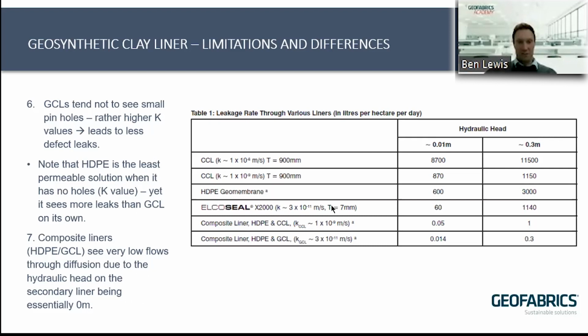And this chart here is showing the impact of a composite liner effect with HDPE and GCL. Clearly the best solution in terms of mitigating leaks and flows. So you can see here HDPE, and this is probably more relevant for landfills with only 300 mm of head pressure, but HDPE on its own, you'd expect maybe 3,000 litres per hectare per day. And that's entirely dependent on leaks, I understand, but this is just an example. Versus a composite liner, which is HDPE and GCL, only 0.3 litres per hectare. So it's a massive, massive difference when you're using composite liners.